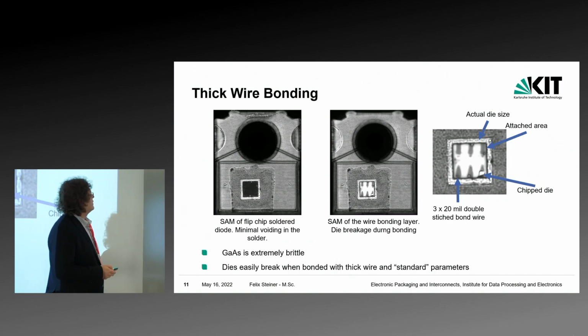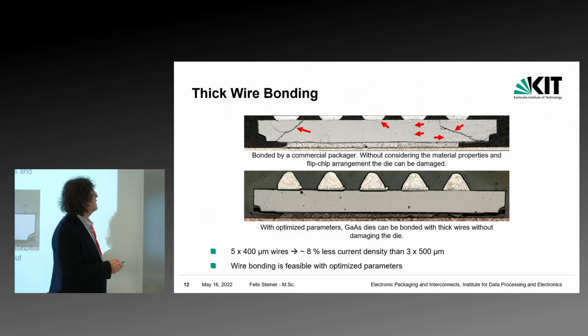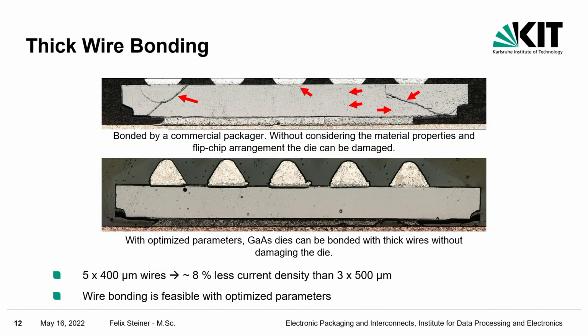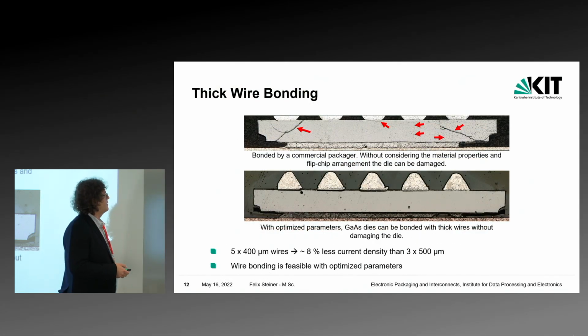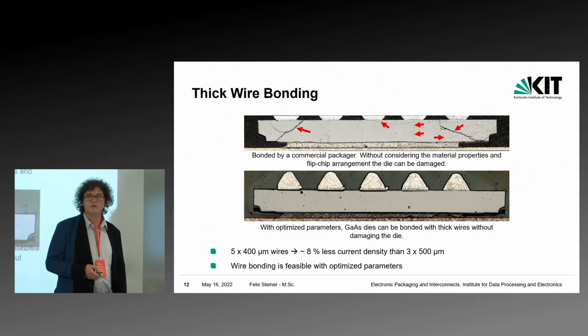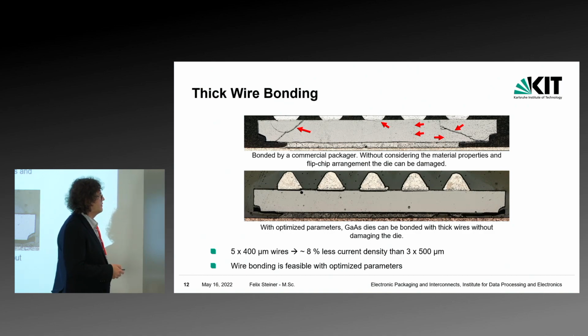If you do not, you see this die here on the top, which was bonded by a standard packager, just with the normal factory standard values. And all the red arrows indicate some sort of breakage inside the die. And that's, of course, not okay. So with some modifications to the parameters, you still get good bonds, but no breakage in the die. So that's also a quite manageable problem.